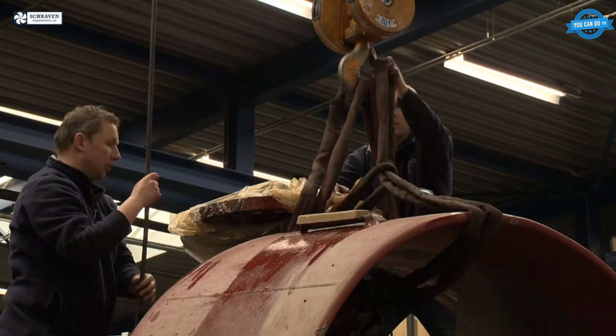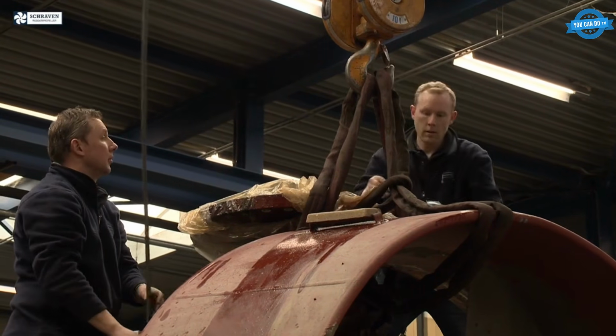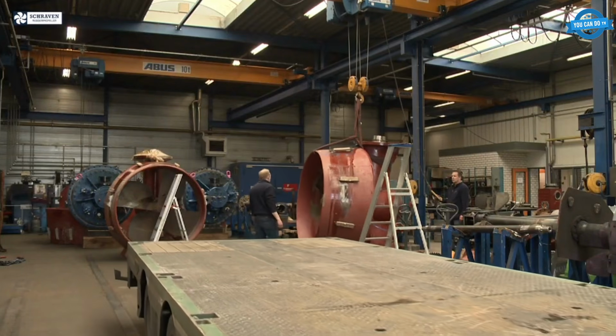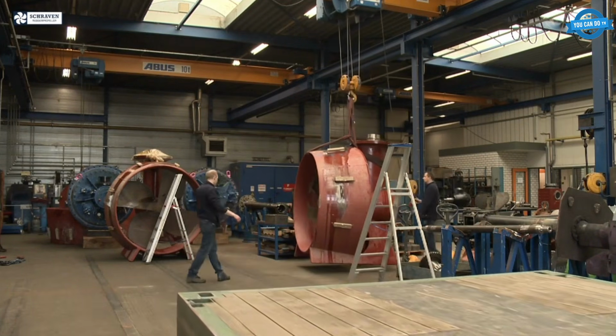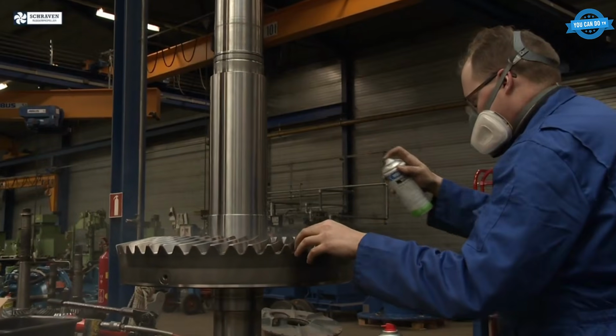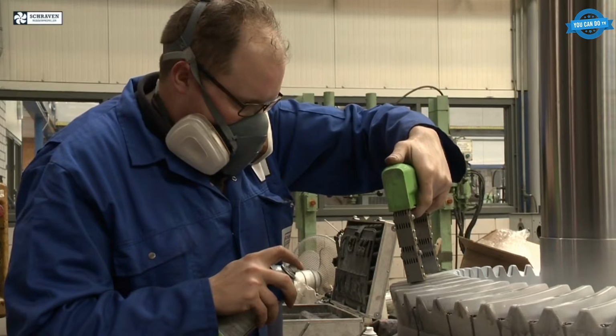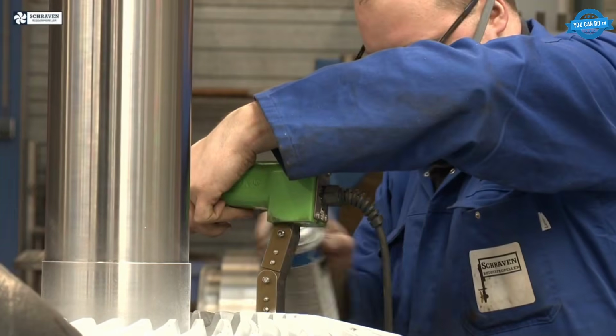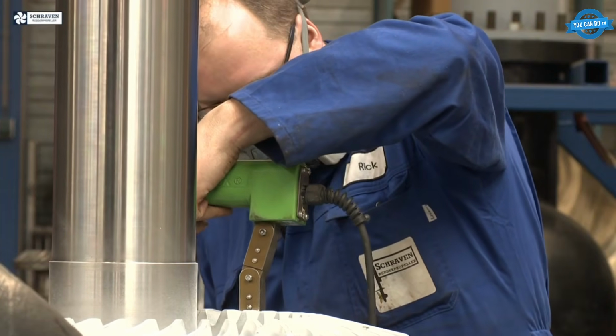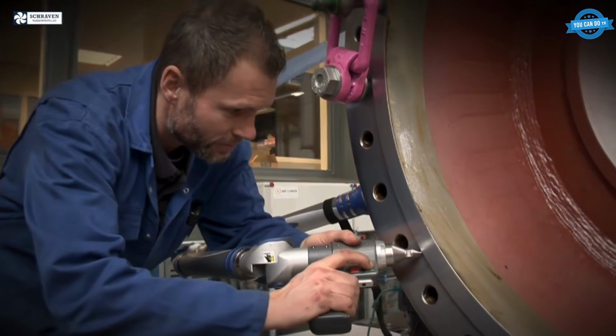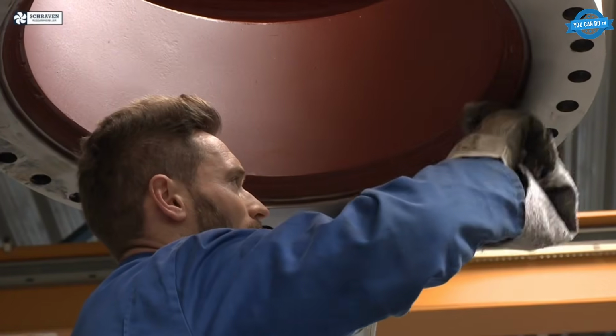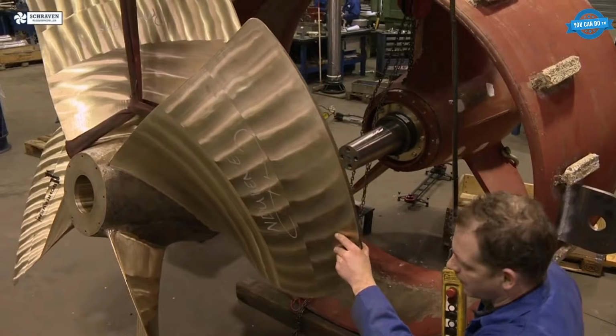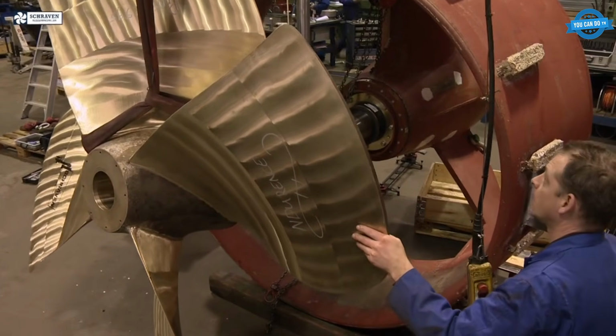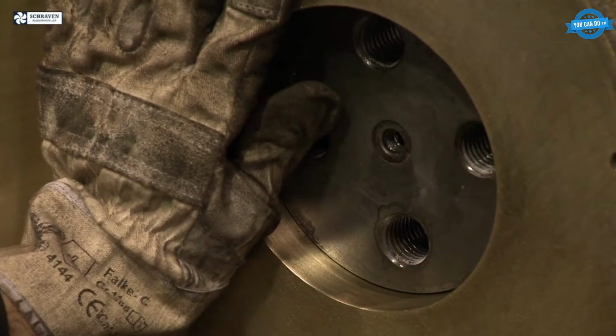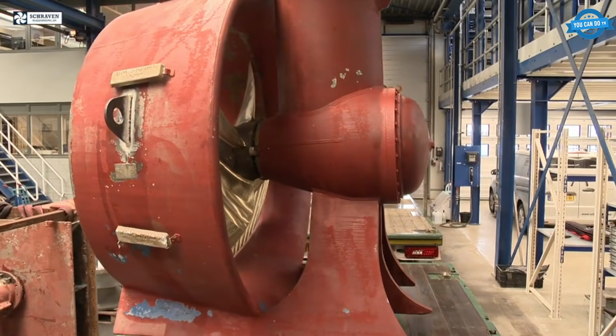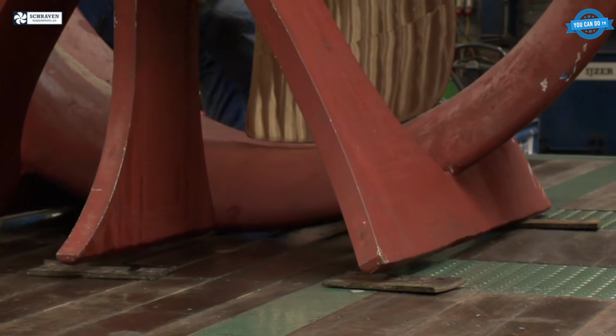The thruster pods are dropped from the underside of the hull by overhead crane, lifted out and trucked to a specialist workshop. There, the housings are split open, the bevel gears stripped and chemically cleaned, and the vertical drive shafts pulled from their bearing seats. Mechanics measure clearances and geometric tolerance at every bolt circle, recut threads where needed, and check shaft seal surfaces by hand. The large bronze blades are polished to a high gloss, near mirror finish, so they cut through the water with the least disturbance, the surface chosen specifically to reduce cavitation.